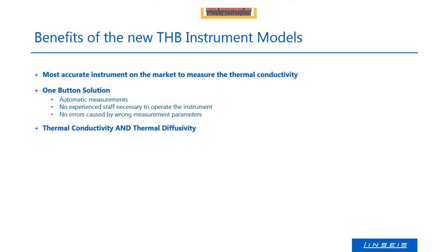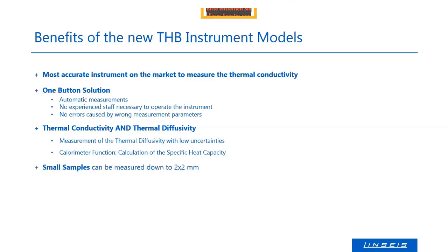The results we get are the thermal conductivity and the thermal diffusivity. Both can be measured with low uncertainties. And if we know the density of our sample, we can calculate from these two values also the specific heat capacity. So we can use it as a calorimeter as well. We can measure small samples. That's also a benefit of this method. The smallest possible sample is 2 by 2 millimeters. I don't know another instrument on the market which can measure such small samples.